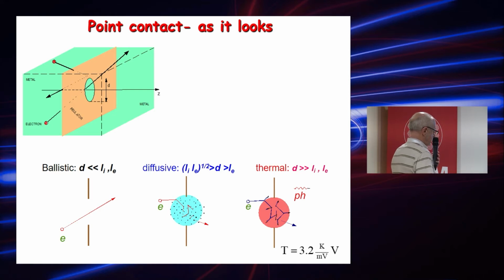Another case is when the size of the point contact is larger than the elastic and inelastic mean free path of electrons. In this case, all energy dissipates in the point contact, and the point contact can heat up. For example, for a standard metal with fulfillment of the Wiedemann-Franz law, the temperature in the point contact increases with applied voltage by 3 K per millivolt. It means if you measure a point contact at helium temperature, applying only 100 millivolts, you can heat up the point contact up to room temperature.